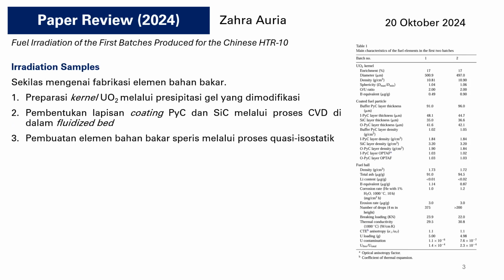Okay, this is a brief on the fuel element fabrication. First, we have to prepare the uranium dioxide kernel through the modified gel precipitation, and then the pyrolytic carbon and silicon carbide coating layers will be formed through the CVD process in a fluidized bed. The last one is the spherical fuel element, which will be formed through the quasi-isostatic process. In Table 1, we have the main characteristics of the fuel elements in the first two batches. As we can see in this table, we have a bunch of information about each coating layer and the kernels, for example, the thickness and the density, etc.